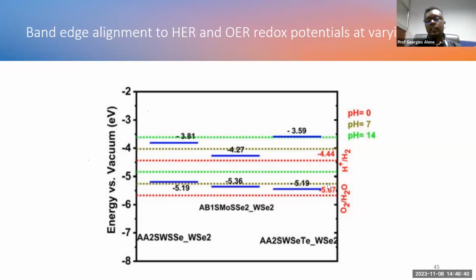redox potential of water. We go actually one step further in this investigation. In the previous investigation, our investigation was only for pH zero value, but here we assume for different conditions the photocatalytic material works. So we consider pH 7 and pH 14 also.